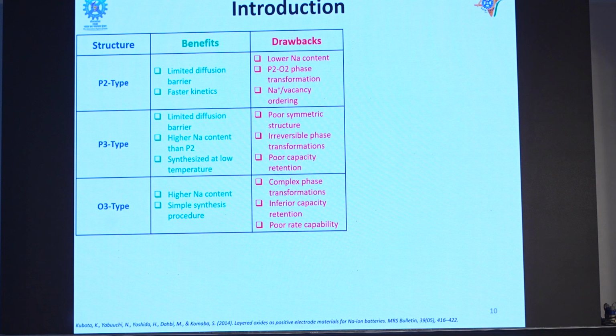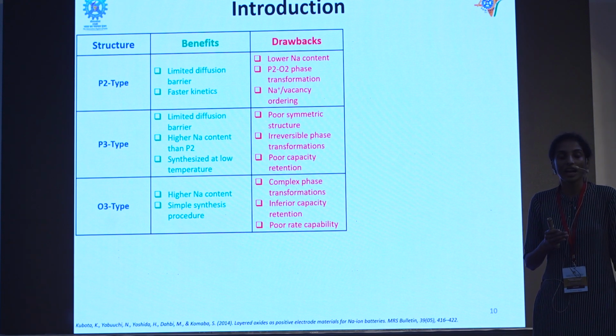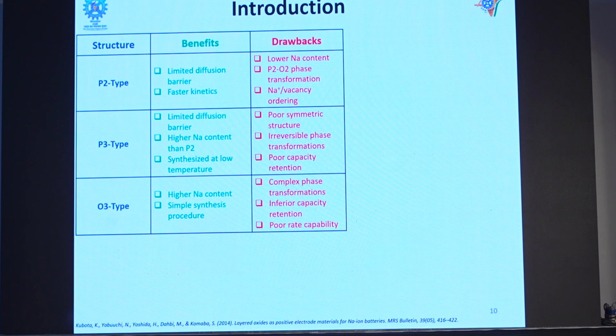So I excluded it. And the P2 type, which is a very common layered material, has a limited diffusion barrier, so faster kinetics. What does it mean? The sodium ions can migrate pretty fast in the system, and as a result, we can charge and discharge our battery at a high speed. When you can charge and discharge your battery at a high speed, that translates to a high power density of a battery. So if a material has a good rate capability, or faster kinetics, it means that you get a battery with a very good power density.